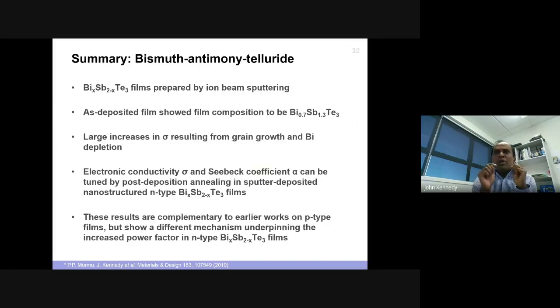So in summary on this one, we're able to make these films under stoichiometric and over stoichiometric. We can increase the grain size growth significantly by depleting bismuth, which obviously changes the electrical conductivity and Seebeck coefficient. These results are complementary to previous ones, but we showed a different mechanism for why the power factor is increased, due to simply playing with the stoichiometry. So after this, we applied it to one of the heat exchanger plates.